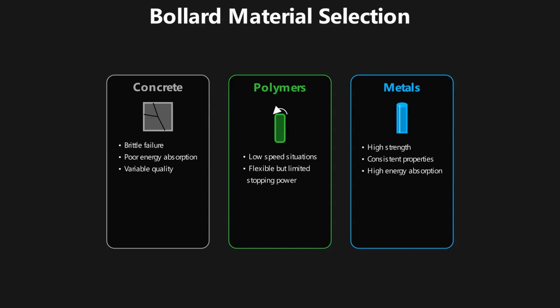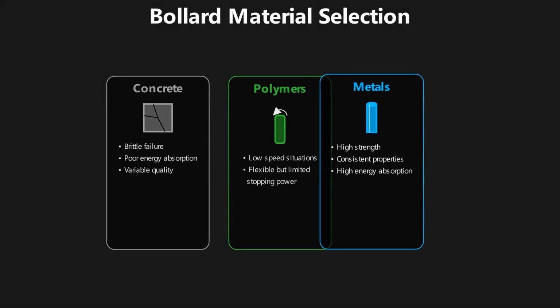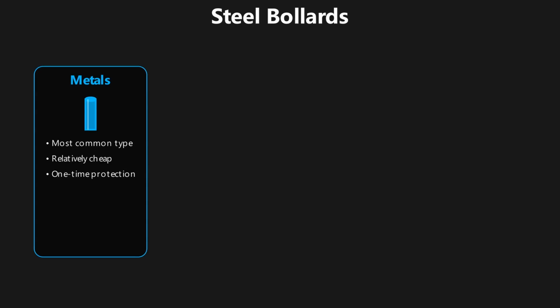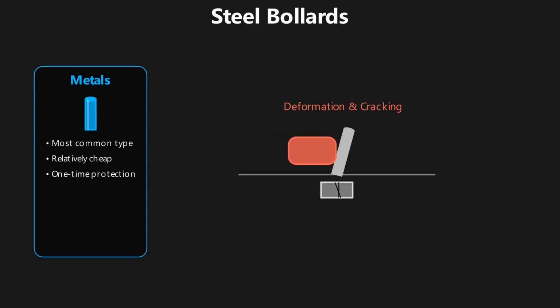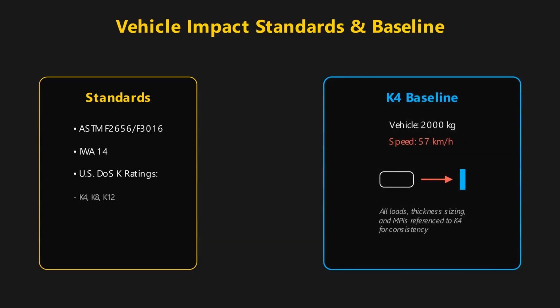Bollards are sometimes made out of concrete, but concrete is highly brittle, has poor energy absorption, and its quality tends to be variable because of mix, curing, cover depth, and rebar placement in the concrete. Polymers, on the other hand, tend to be for low-speed situations. They tend to deform and then get back into place below a certain speed. Therefore, we are conducting our study on metal bollards. Several standards define vehicle impact performance for bollards, including ASTM F2656, F3016, IWA14, and the legacy U.S. Department of State K ratings K4, K8, K12.